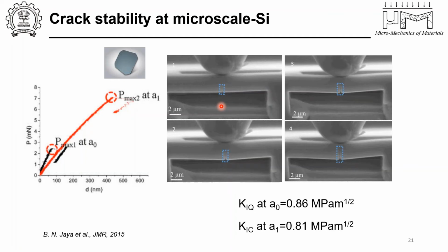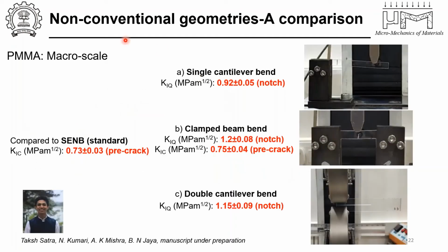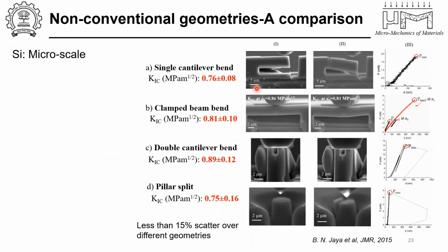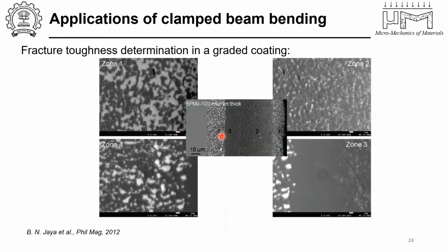So crack stability was something that we demonstrated. Very quickly, we compared it to other geometries which were non-conventional that were being used at the micron scale. For example, the single cantilever bending, the double cantilever bending, and so on. And we saw that for all of these cases, within about 15% difference, all of them perform pretty well, given that some standards are followed with respect to the calculations of the geometric factor. Same at the micro scale, we looked at single cantilever, the clamp beam, the double cantilever, and the pillar splitting geometry, and all of them sort of gave very similar values of fracture toughness.